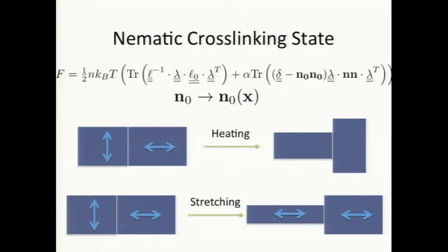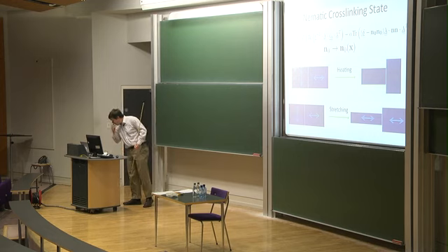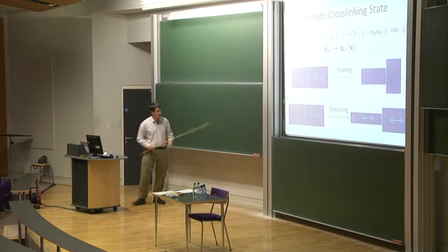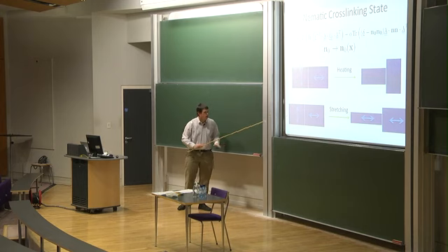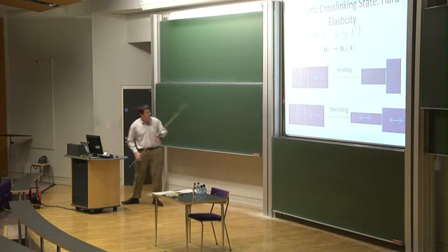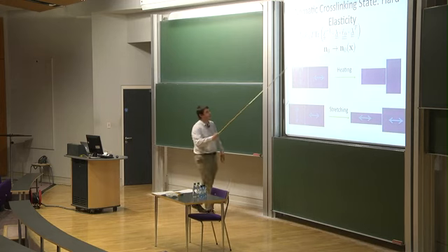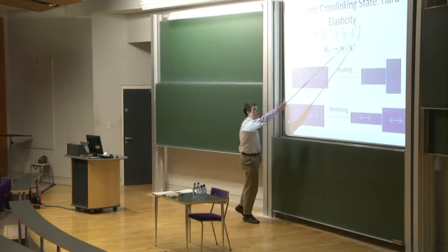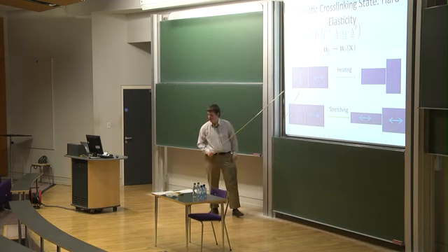Okay, so you might complain I've drawn pathological cases here with really sharp domain boundaries, which is not something a liquid would do. But the nice, smooth versions you would see in a liquid are just as bad. That's a little bit harder to see they're bad. Okay, so this is then the basic intuition, right? The domain structure was chosen in the liquid state, and therefore we don't get any possibility of cooperation between the domains. And in fact, the idea here then is we don't even need, probably, any anchoring part of this energy to explain why these things have a hard response.